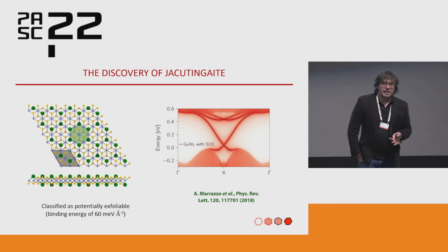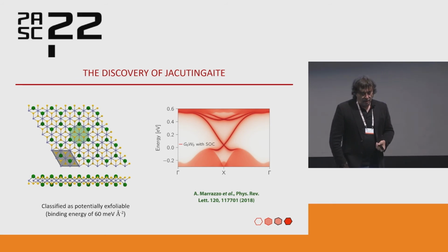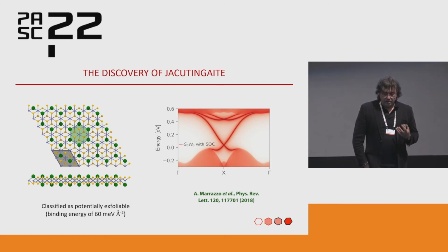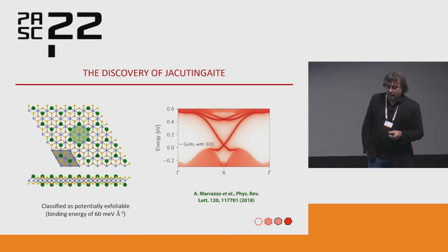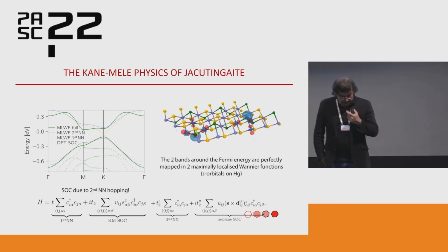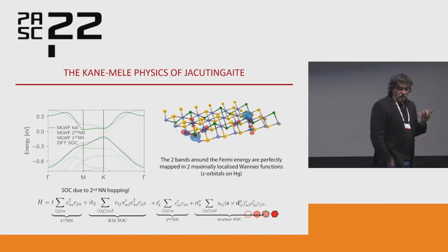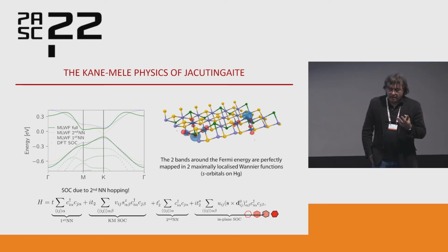And this material looks exactly like graphene. You see this hexagonal lattice of mercury atoms, but they are very heavy, so the spin-orbit coupling is very important. And if we do a state-of-the-art calculation of the band gap with many-body perturbation theory, this material has a huge band gap, half an electron volt, and you see these are the edge metallic bands, so it's a topological material in the bulk, but with these bands. The detail here becomes a bit technical, but this turned out to be the first and the only topological material that actually embodies the physics that was envisioned in 2005 by Charles Kane and Gene Mele.